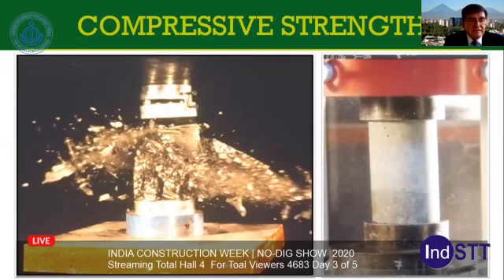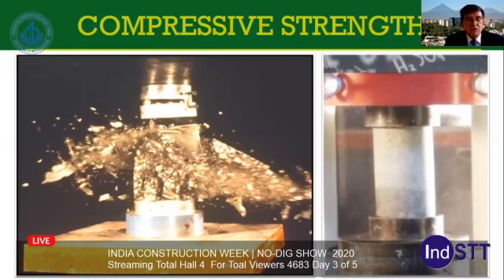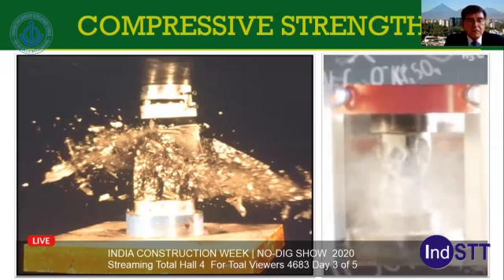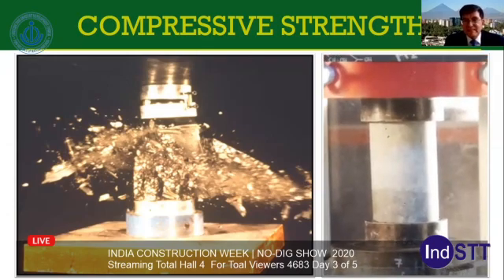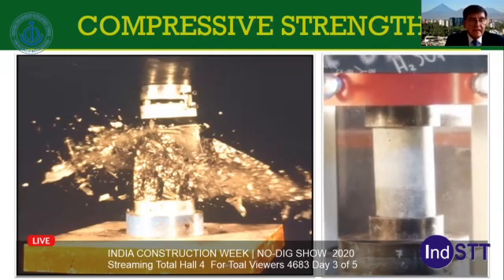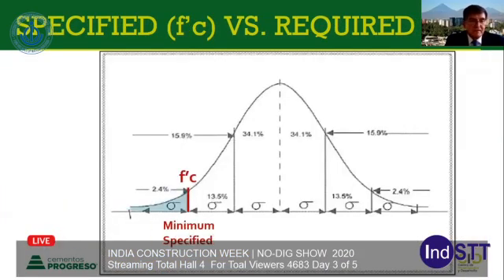For example, starting with the compressive strength. We sell the majority of our concretes by compressive strength, and it's one of the most important parameters that we measure in plants and projects. In our case, we sell by minimum strength. You know, we could see here a normal distribution of strength results, and to achieve that minimum strength, we have to be able to achieve a required mean strength, where the results are gathered. We need that to achieve the minimum strength. We have to give more strength as a mean. But the problem is that